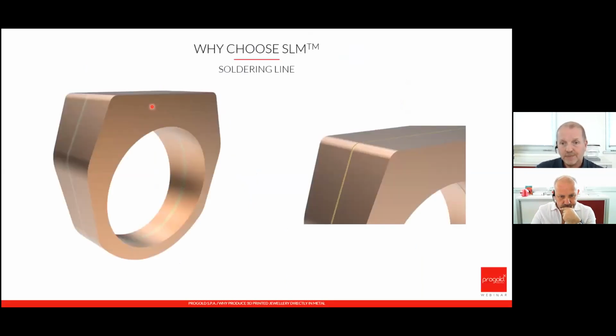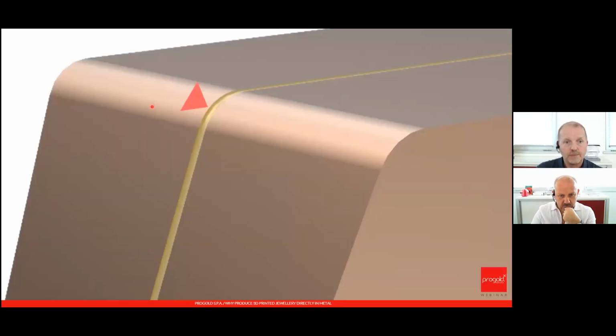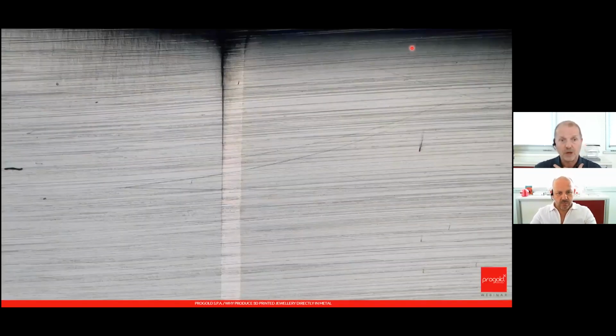This is the soldering line, and we saw that assembly needs soldering. Here we have the soldering line. And this is a real picture, okay, with a visible soldering line. In case of rose gold, the line is more visible than in other case, and there is also in rose gold and in the other colors a shrinkage due to different surface hardness. Probably in the top of this picture, you can better see what I mean as a shrinkage.